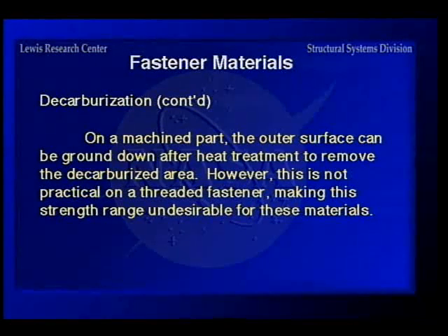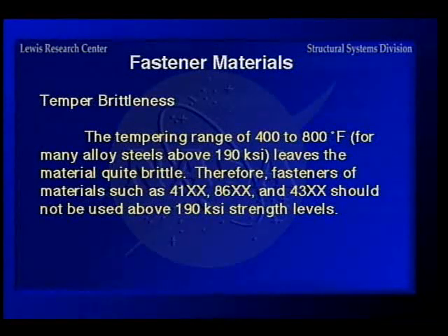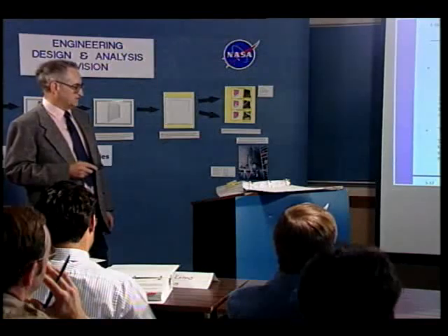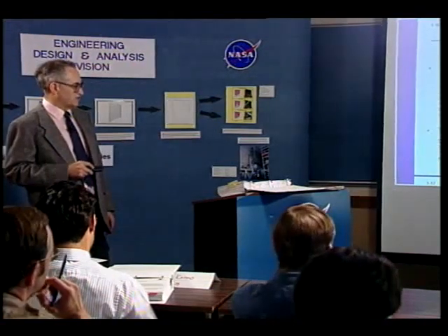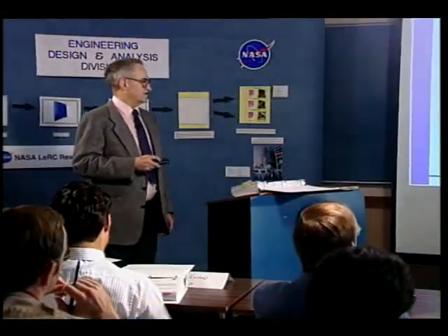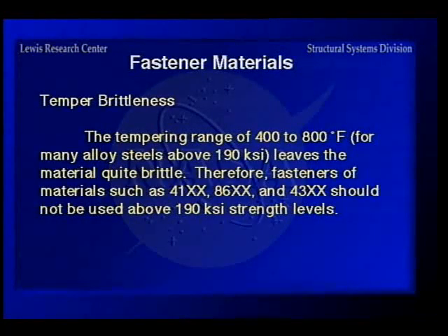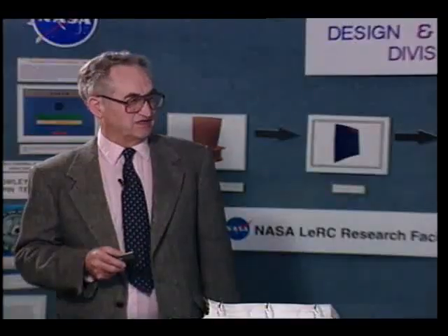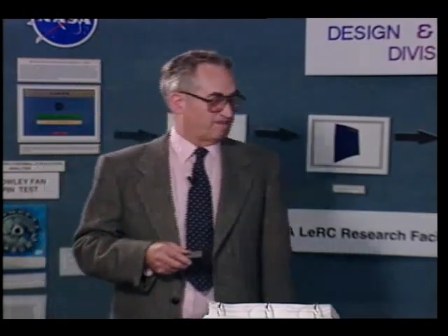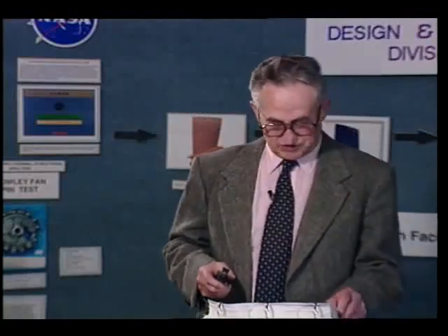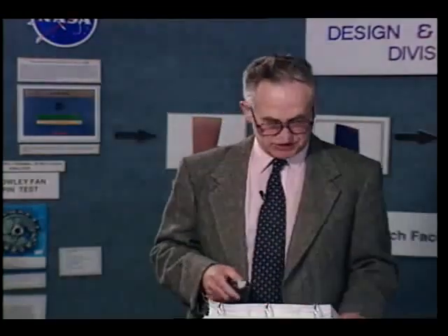Now, temper brittleness is another thing you can run into on the high-strength fasteners. After you have quenched them, then you need to go back and temper them, which means holding them at a fairly low temperature to get the strength that you need. But that also causes the material to be brittle. So carbon steel fasteners above 190 KSI are a real risk as far as having brittle failure. Now you can use some of the super alloys at strengths higher than that, but not the ordinary carbon steel. Now going to carbide precipitation.